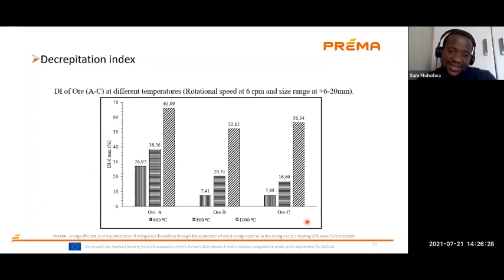Then we go to the decrepitation index. Remember, one of our set questions was to find out how temperature affects the decrepitation index of this ore. Here we have Ore A, we have 600, 800, and 1,000 here. As you can see, as you increase temperature, the decrepitation index of particles that are less than 6 millimeters increases. The same applies with Ore B, and the same applies with Ore C.